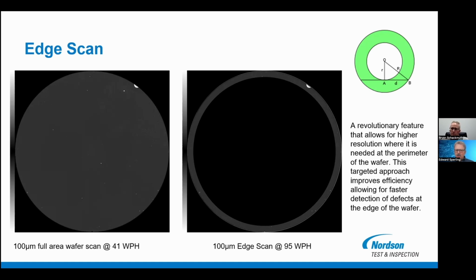So with this, you really have the ability to zero in on a piece of the wafer, right? A particular zone within that wafer. Yeah, so in X and Y, we can vary the scan size and look at different regions. But with acoustic, you can also vary it in the Z dimension. So we can look at the top few layers or the middle layers or the bottom layers. We set what's called an electronic gate based on the time it takes the ultrasound. We can set it for a specific time period in the wafer, and then we can isolate just that layer. So if you're more interested in defects that are deeper within the wafer, we can focus the ultrasound there and show those defects with more contrast and resolution.